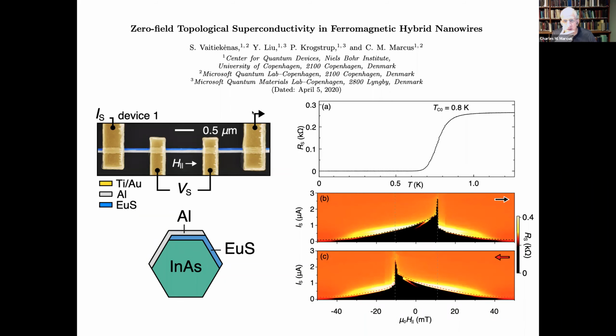So let's take the combination that produced those Majoranas in nanowires and add to it a europium sulfide layer, with the idea that we'll be able to produce the kind of ferromagnetic exchange that will act as though we've put the system in an external magnetic field, and ideally create the kind of physics that one could create by putting the thing in an external magnetic field. So here's a cross-sectional picture of the nanowire. It's a hexagonal nanowire, 100 or so nanometers across.